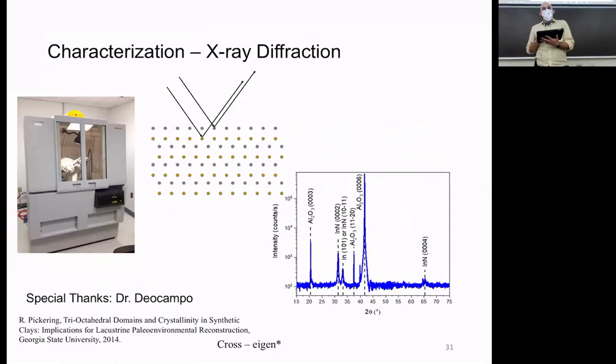The other thing that we did was X-ray diffraction. Now, some of you may have seen upstairs, we have a little X-ray machine. It's just a tiny bit smaller than this one over here. This one takes up most of an office space. The one upstairs sits on a bench top. So they work the same, though. It's kind of interesting. What happens is X-rays are shone onto our sample, and the waves will interact with each layer of the material. And as they interact, we again get diffraction patterns that correspond to the spacing between layers, the spacing between atoms across this direction. And we can measure then, again, the crystal structure and the crystal quality.